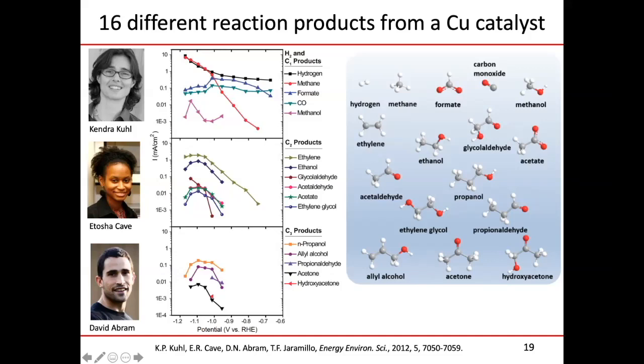Another issue is that you have to apply very negative voltages. The equilibrium potentials for most of these reactions are around 0 volts versus RHE, so similar to hydrogen, and yet you have to dial up the voltage to about -1 volt before you get these chemistries to go at a reasonable rate. Another issue is that a lot of the more valuable products here that are easier market entry points are oxygenated molecules, things like, say, ethylene glycol or acetaldehyde. But oftentimes, the hydrocarbons are what are favored, like ethylene and methane. Now, those are great molecules. I cook with methane every single day on my stovetop, but those are also really inexpensive.